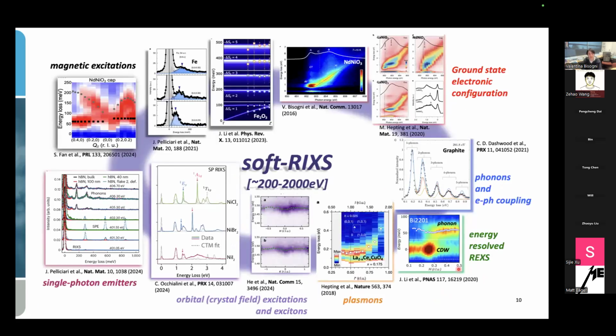And as a general overview, if we talk about resonant inelastic X-ray scattering in the soft X-ray energy range, so between 200 and 2000 eV, we can actually study a large variety of excitations. Of course, since this is the main topic of this talk, we can probe magnetic excitations and their momentum dispersions in a large variety of materials, always provided we can satisfy the resonant conditions. We can understand the ground state electronic configurations of materials. It is possible to measure phonons, and through the multi-phonon branches, one can extract electron-phonon coupling.